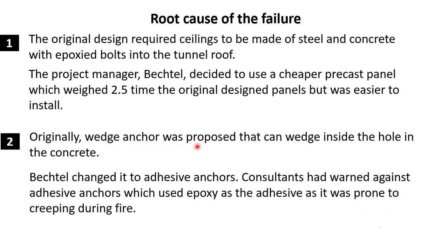Second, originally a wedge anchor was proposed that can wedge inside the hole in the concrete. So a wedge anchor is another way of fixing something to concrete, and I will show you the picture of a wedge anchor. Bechtel changed it to adhesive anchors. Consultants had warned against adhesive anchors which used epoxy as the adhesive as it was prone to creeping during fire. So there was already a concern that adhesive should not be used inside a tunnel because if fire breaks out in the tunnel and there are people inside, cars and vehicles all inside the tunnel, then it will lead to the failure of the joints and thus collapse of the ceilings. So this was already mentioned by the consultants.